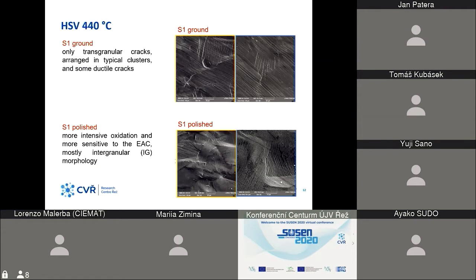However, after testing at high temperature, we found more extensive oxidation, and the specimens were also found to be more sensitive to EAC. On the polished surface of the specimen loaded by the lowest test rate, there were observed cracks showing mostly intergranular morphology, and on the ground surface there were observed only transgranular cracks. They were also sometimes arranged in typical clusters, and we also found some ductile cracks.